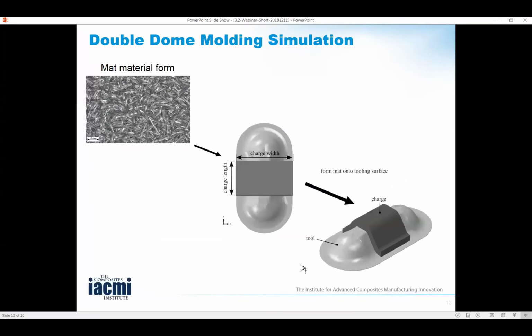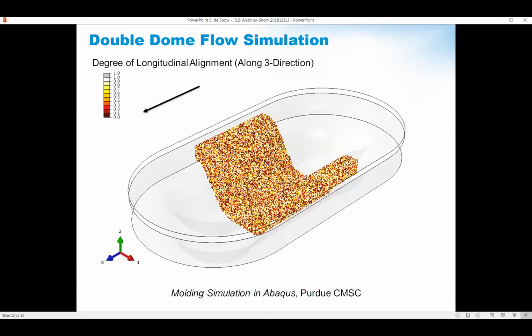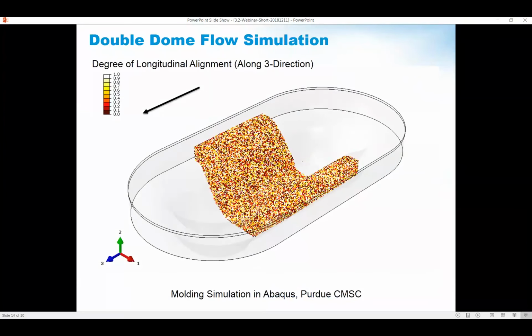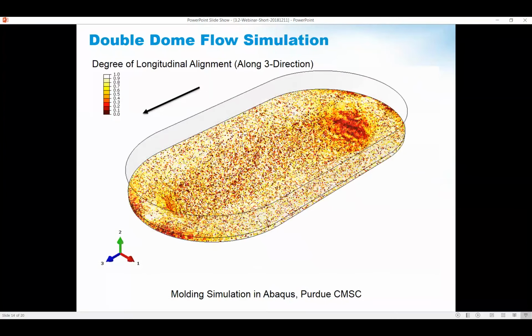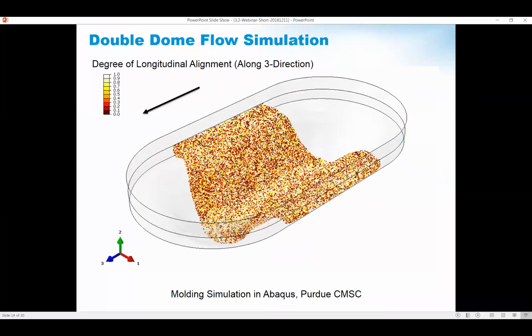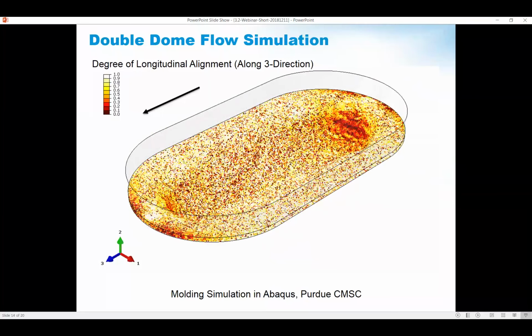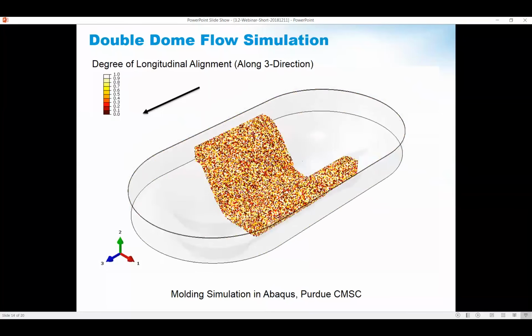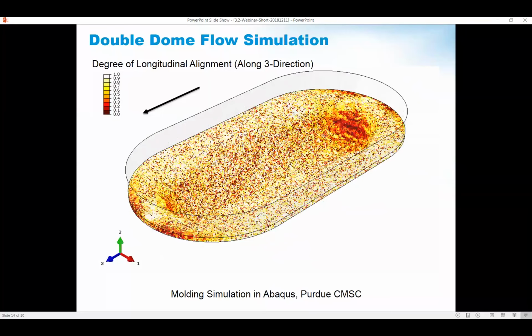I'll note that in our simulations, we account for the effects of reorientation that occur as you take that charge and drape it onto the mold. Shown here then is an initial charge, which is informed from the orientation state that we measured, and then the draping effects. And now I'm going to show you an animation of a simulation of the forming process. You see the two molds coming together and the flow from that initial alignment all the way to a full part. You'd say that this is a successful molding trial in the sense the part completely filled, but then also you'll note that there's formation of what looks like a knit line there at those lateral extremities, longitudinal extremities of the part.